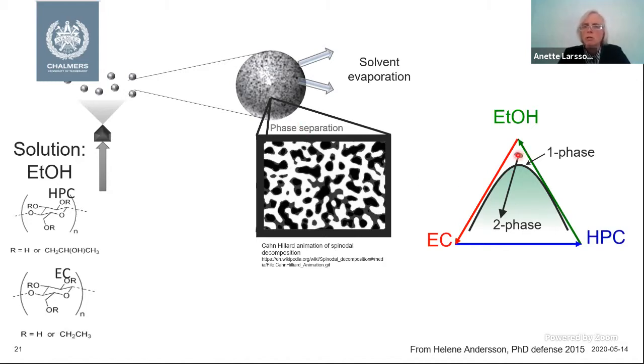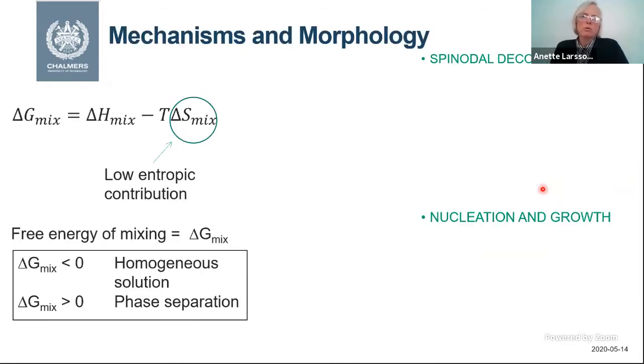So when we have phase separation, we start in one phase, and the polymer was dissolved in ethanol in this case. When you have the coating process, then you dry the system. So ethanol is evaporated here, and then you get a higher concentration, and the polymers precipitate and form the coating. So what you start with here is one phase region, and when you evaporate away the ethanol, the concentration of the polymer increases, and you reach a two-phase region. In this two-phase region, you will have one phase with this polymer concentration and one phase with that polymer concentration. And this is, of course, due to the low entropy contribution for polymers.